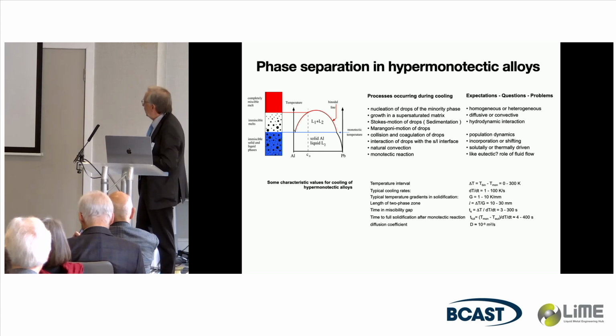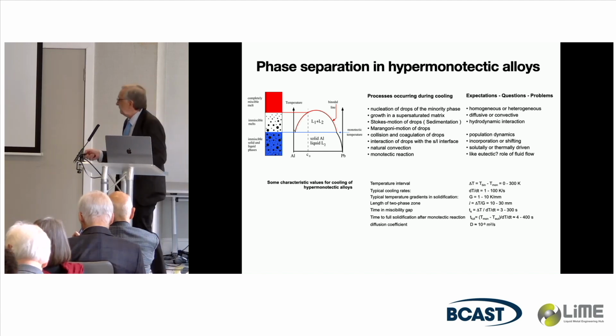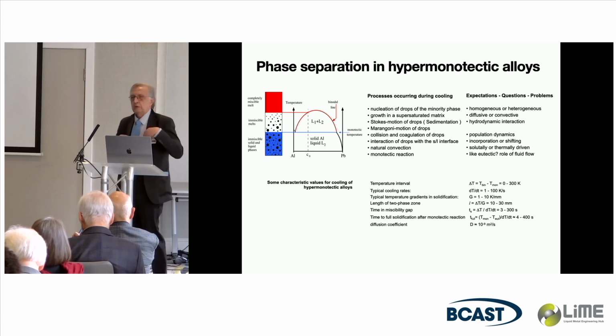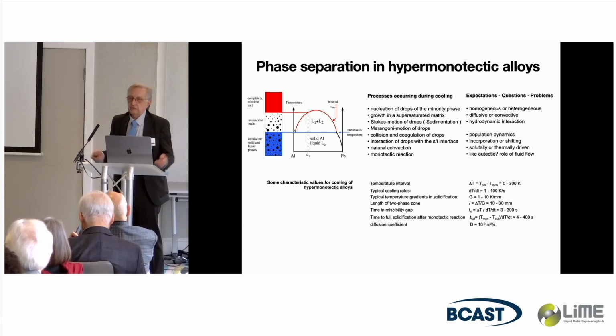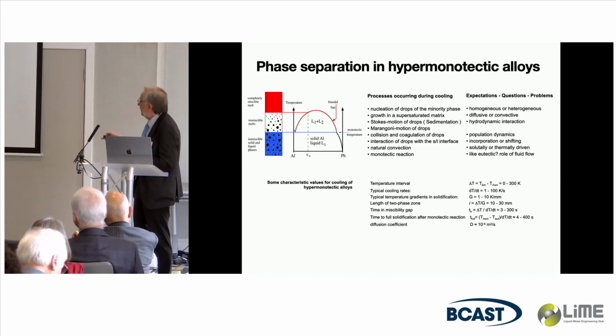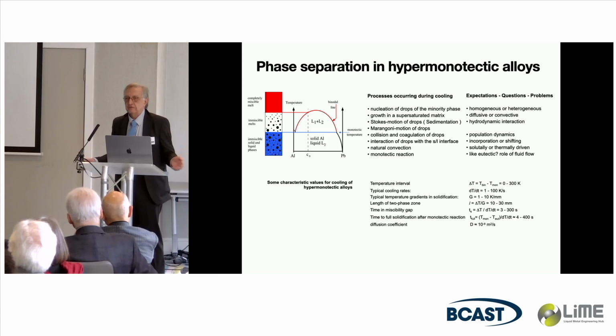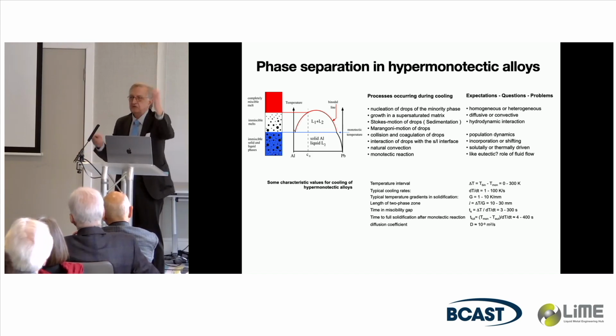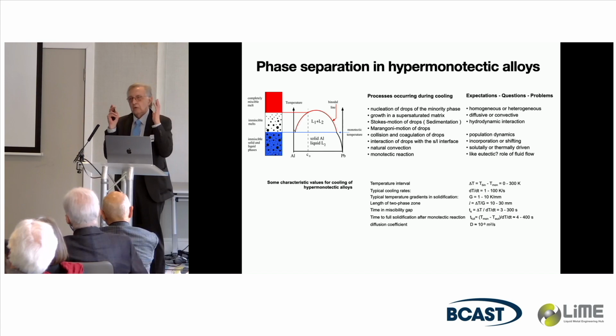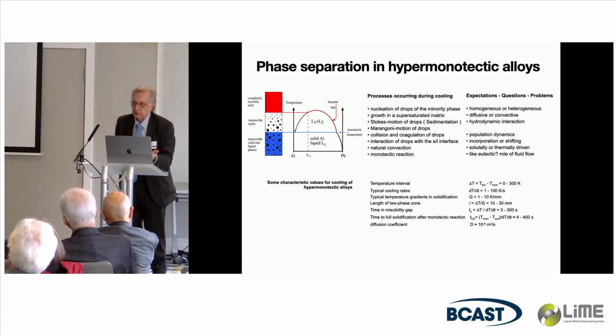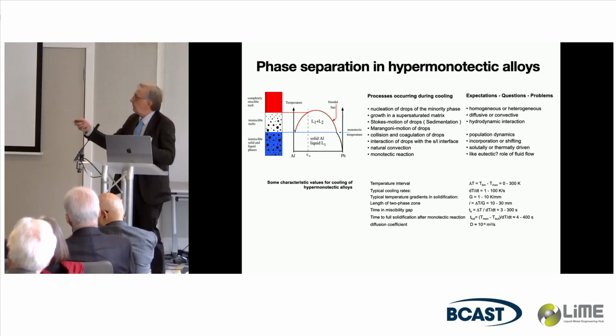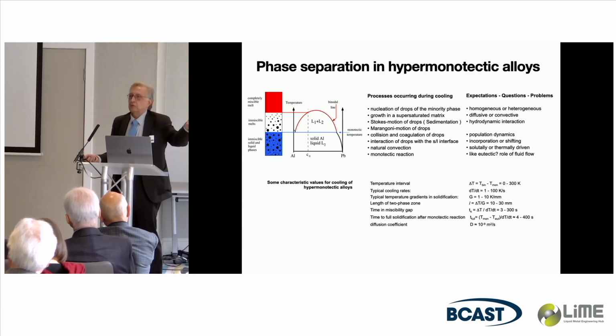And coming to a few points, as I said, this temperature interval is typically around 100 to 300 Kelvin. Cooling rates are, in a typical directional solidification experiment, 1 Kelvin per second up to maybe 100 Kelvin per second. So it takes around 10, 20, 30, 40 seconds that the droplets which appear have time to do some motion and to produce some microstructure. You see in the end in a solidified sample a microstructure, and you have to reconstruct with all the possibilities here, how did this microstructure really form?